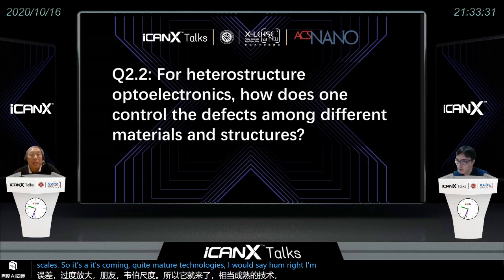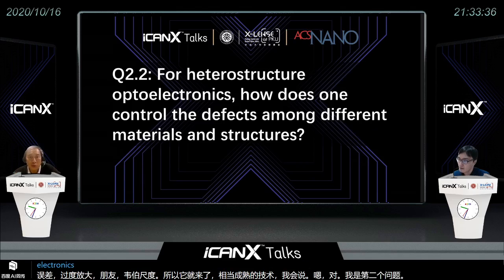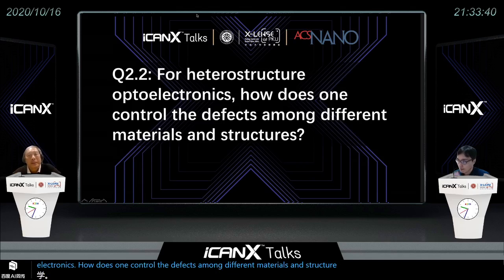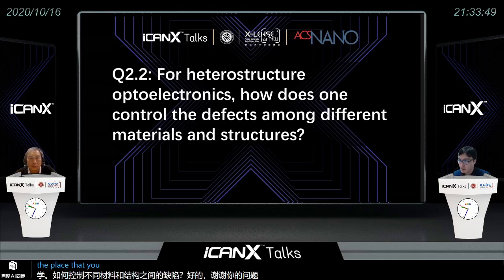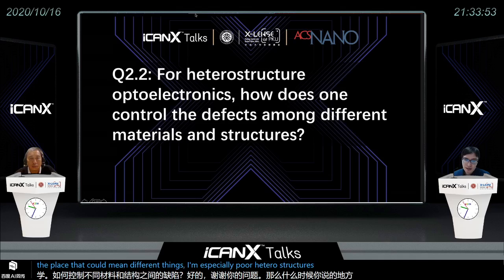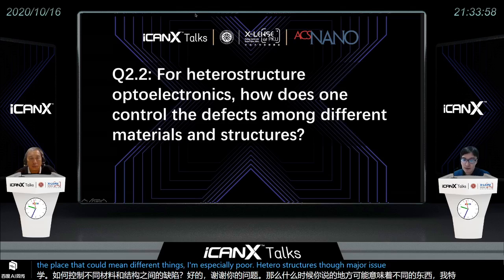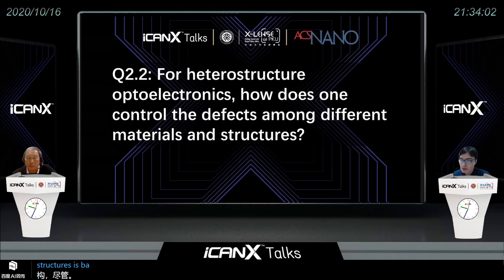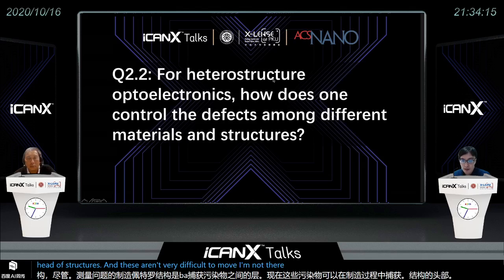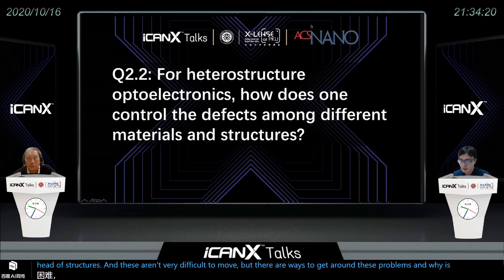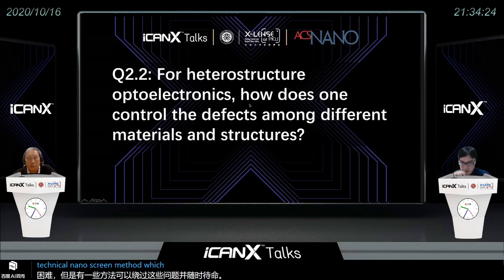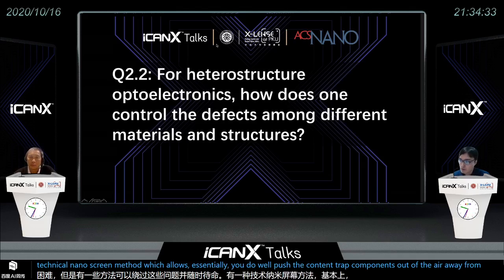The second question: for heterostructure optoelectronics, how does one control the defects among different materials and structures? Okay, so thanks for the question. When you say defects, that could mean different things, especially for heterostructures. One of the major issues of fabrication of heterostructures is the trapping of contaminants in between the layers. These contaminants can be trapped during fabrication, and they are very difficult to remove. But there are ways to get around these problems. For instance, there's a technique called the nano-squeegee method, which allows you to push the trapped contaminants away from your device region.